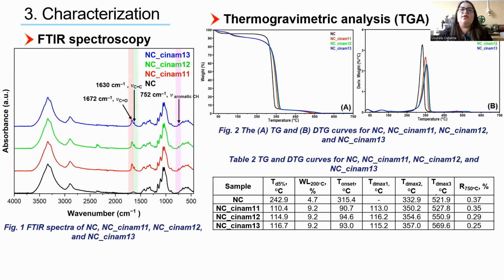The FTIR spectroscopy confirmed that the impregnation of the nanocellulose sponges with cinnamaldehyde took place successfully. We can see that a new peak appeared at 1672 cm⁻¹, corresponding to the stretching vibration of the C=O bonds in cinnamaldehyde. Also, a new peak appeared at around 1630 cm⁻¹, which corresponds to the stretching vibration of the C=C bonds in the aromatic ring of cinnamaldehyde. And the third peak appeared at around 752 cm⁻¹, and corresponds to the bending vibration of the C-H bonds from the aromatic ring of cinnamaldehyde.